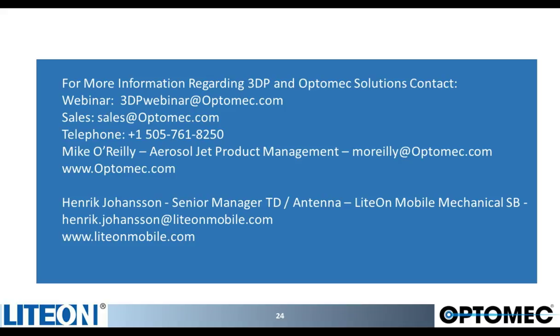And that's primarily driven by the desire of many consumer electronics manufacturers to get to much lower temperature materials such as PC, ABS. And the only way we seem to be able to reach the temperatures and get to the kind of resistivity values that customers are looking for, which are typically 2 to 4x resistivity over the base value of the material or the ink, is to get small nanoparticles, such as particles below 10 nanometers in size.